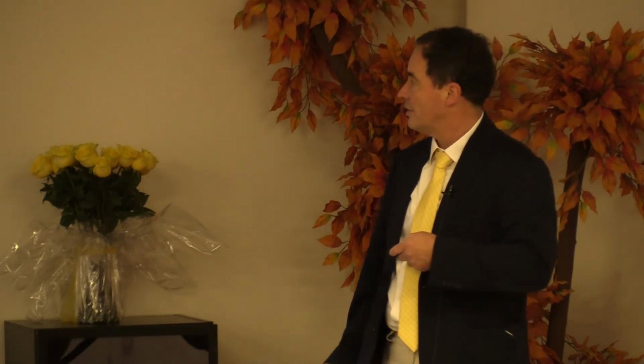And in the other case, the molybdenum silicon titanium alloy, we still do not fully understand why this alloy is so oxidation resistant, because, as I mentioned earlier, we tried to set up a model for discriminating the oxide scale thickness which forms on the outside and which forms on the inside.